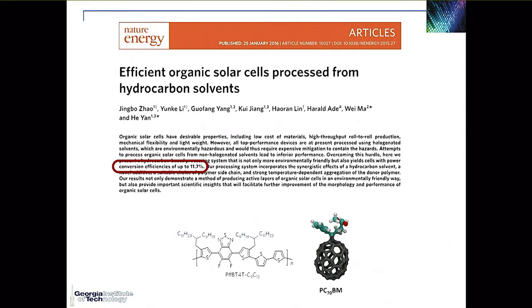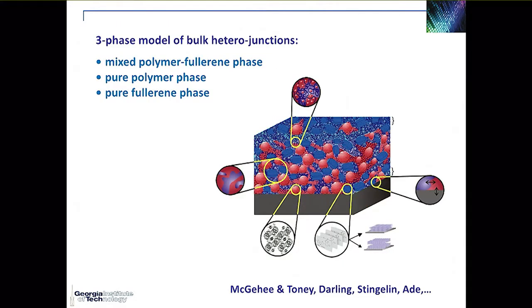like Yongfang Li at the Chinese Academy of Sciences, have efficiencies that are on the order of 12%. In the case of those here, this is the polymer-fullerene solar cell of He Yan. You need to have a large interfacial area between your electron donor and your electron acceptor, because that's where exciton dissociation can occur. And so in many instances, and this is the architecture that has been prevalent since about 20 years ago, you get a blend of your donor and your acceptor, and very often that means that you get at least three main phases: one that is a pure fullerene phase, one that is a pure polymer phase, and then a mixed polymer-fullerene phase in the so-called bulk heterojunction.